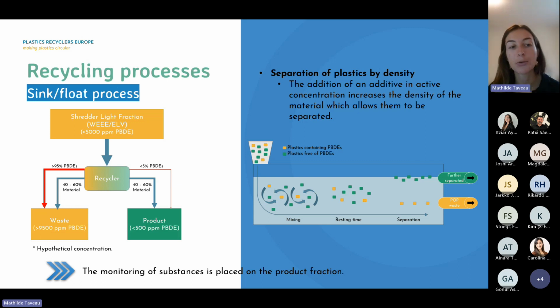Here, this is what you see in the drawing on the left. So you really have a fraction that floats, that's the product fraction that is compliant with the 500 ppm of PBDEs, which is a brominated flame retardant, or rather a category of brominated flame retardants. And then you have a waste fraction. The waste fraction is the fraction that is sinking, and therefore it's sent to disposal because here it would be considered as a waste. This is what you can see also on the right.